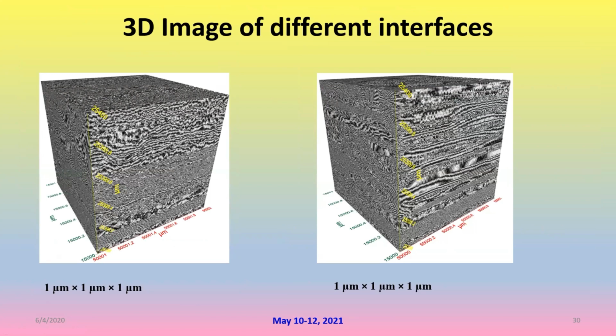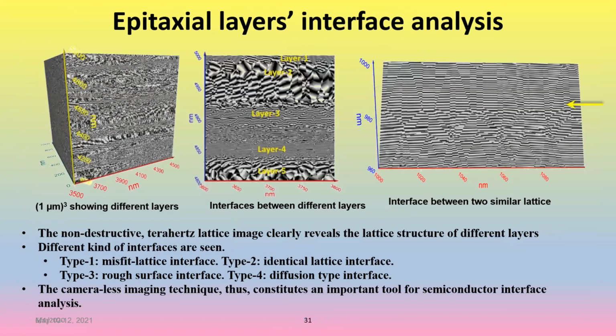We can now see, when you see the very close 1 micron by 1 micron by 1 micron volume, we can see different layers of the interfaces, how they are deposited. And then we can characterize those interfaces. On the middle, you have this layer 1, layer 2, layer 3, layer 4, and layer 5. And between each of those layers, we have different interfaces.